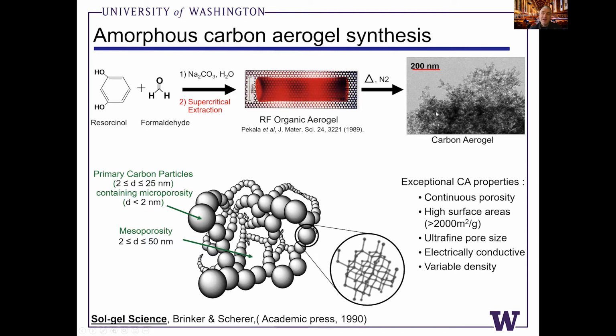So these are amorphous carbon aerogels that have unique properties. They were originally developed for high surface area electrochemical supercapacitors, but they have some very high surface area and high porosity properties that make them very useful in growing nanodiamonds. So each of these little cartoon spheres you can think of as amorphous carbon. It's at least 99.99% carbon. There is hydrogen left over in the material. We can't get rid of all of it. We estimate it's on the order of maybe ppm level hydrogen from infrared absorption spectroscopy.